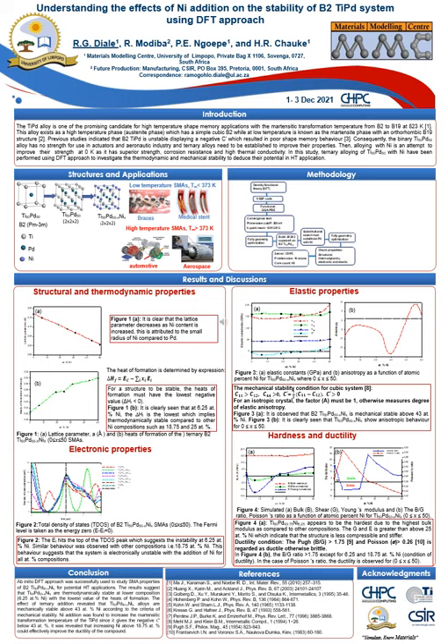In conclusion, using a first-principles DFT approach, we successfully studied the shape memory alloy properties of titanium palladium nickel alloys. This system was found to be mechanically stable above 6.25 percent of nickel. It was also revealed that increasing nickel above 18.75 percent could effectively improve the stiffness of the material.